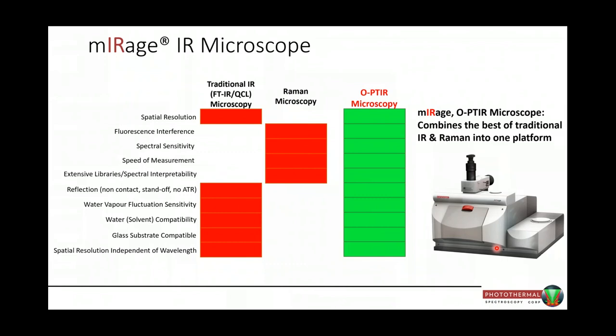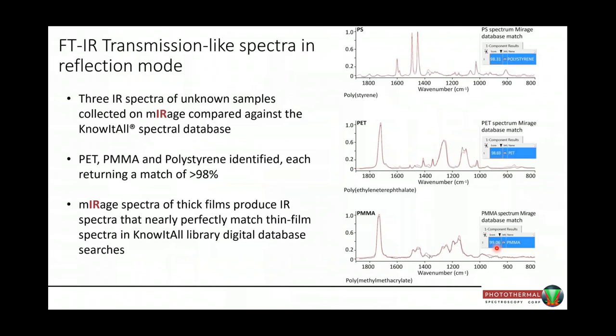Spectra look just like transmission spectra, even though they're measured in reflection mode. So these are three relatively thick polymer samples that you would not be able to normally transmit light through in a regular FTIR. We can collect spectra in reflection and search them against databases of IR spectra, and we get perfect matches with spectra that were collected on thin films in transmission. There's a black spectrum and a red spectrum overlaid. The red spectrum is the library, and the agreement is really, really good between the spectra.